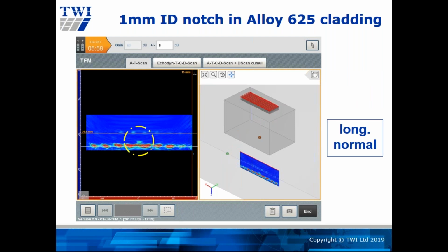If we look at the same flaw now with the longitudinal normal wave, what you see now is the back wall, a very strong back wall. And then you can see a signal there from a 1 millimeter notch from the inside of the cladding. These dots are the interface between the carbon steel and the cladding. Those interface signals are useful for establishing the thickness of the cladding, but they also illustrate the changes in metallurgical condition, which gives rise to the echoes from that boundary.